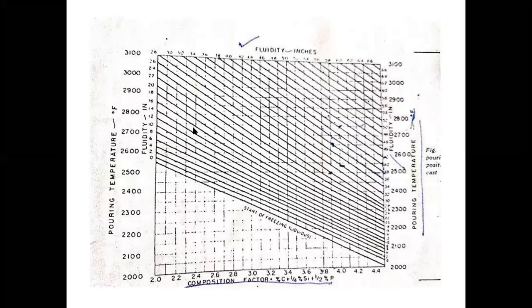I guarantee rejection due to blowhole by using cold box core and green system will be 0.5% max. Rejection due to blowhole even after machining will be 1% max. If we do the proper gating system in any foundry, sand rejection and blowhole rejection totally will be around 3 to 4% or 5%. But if we do proper pouring time calculation, rejection due to blowhole will come to less than 0.5%. That is why it is most important to do this calculation, and practically I have proved it.